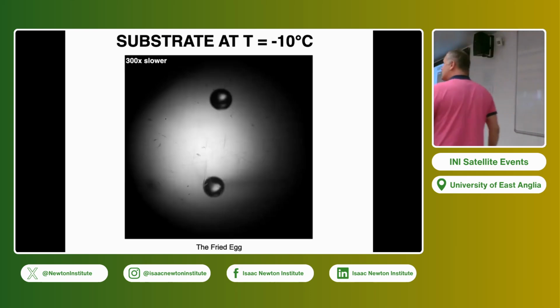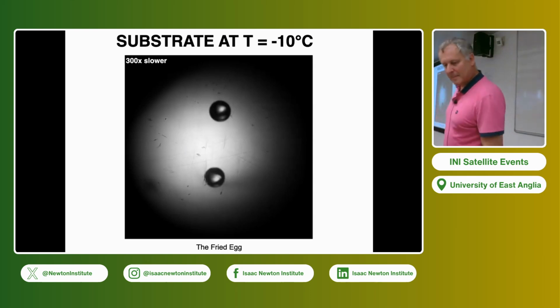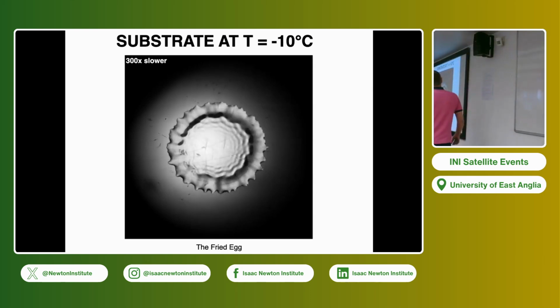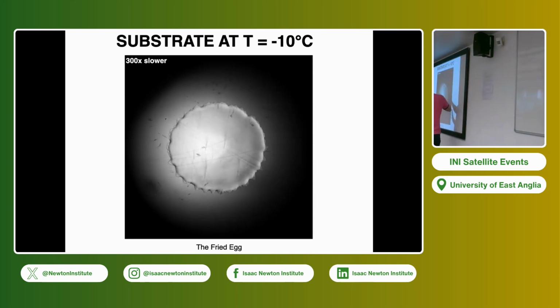Let's do the same thing, same drops, same velocity on the same substrate, but now the substrate is at minus 10 degrees Celsius. So you see, I will stop the movie now. It has reached a maximum diameter again, which, we will see, is not too far from the one without solidification. But after that, instead of retracting immediately, what you have observed is some capillary waves that were running through the liquid, while at the same time you can see that you have this small layer of ice.